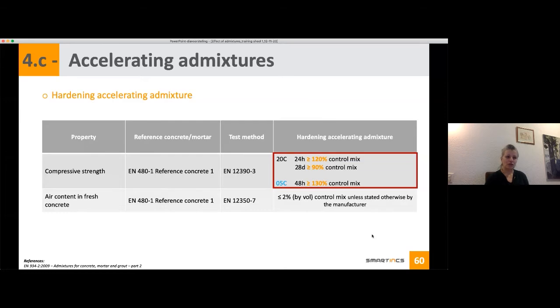You also have a requirement for your strength development at 5 degrees. After 2 days, so 48 hours, your strength should be higher than 130% of your control mix. Air content, in any case, should be no more than 2% compared to your control mix.